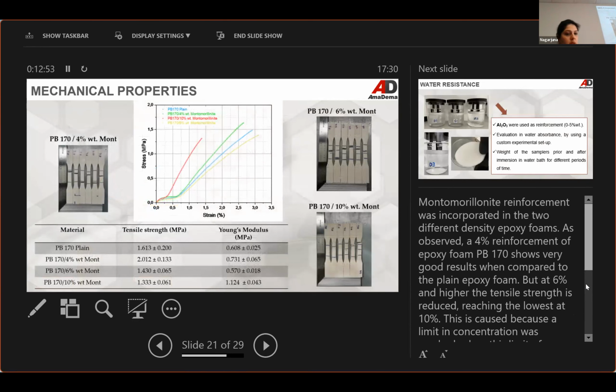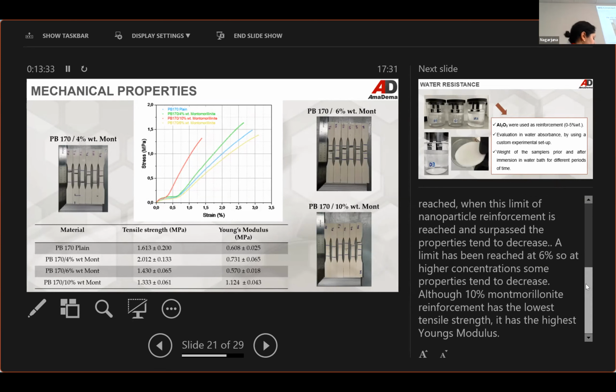Okay, the next system we tested was the montmorillonite nanoparticles at different concentrations. We have used the 170 foam to check this, and we have incorporated 4%, 6%, and 10% montmorillonite nanoclays. And what we observe here is actually very interesting. We see a percolation of the enhancement when we use nano-reinforcements. I'm sure you're familiar with this concept. It basically highlights that above a certain percentage, we do not see the enhancement due to the inclusion of nano-reinforcements, because the interactions between these reinforcements become more significant.